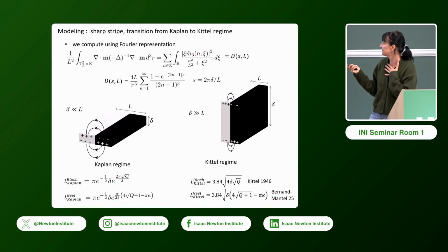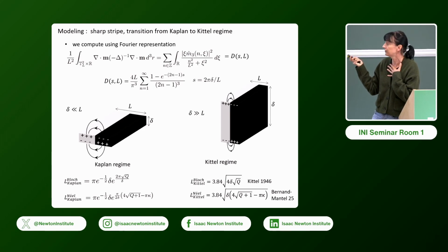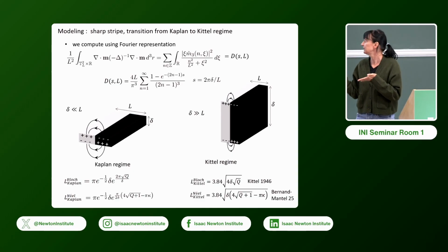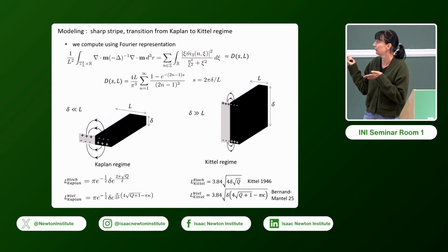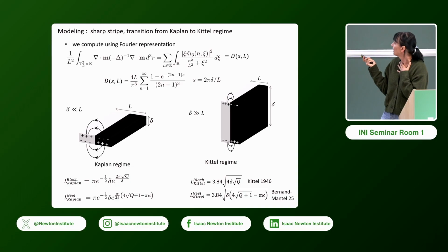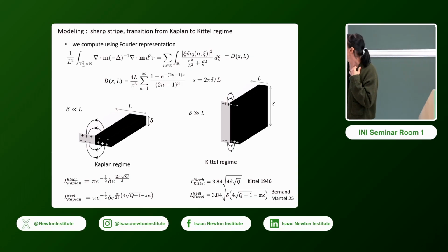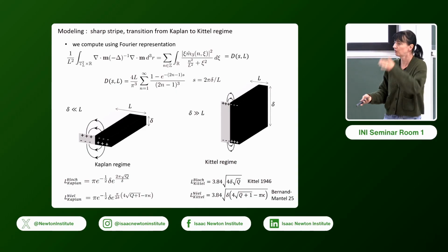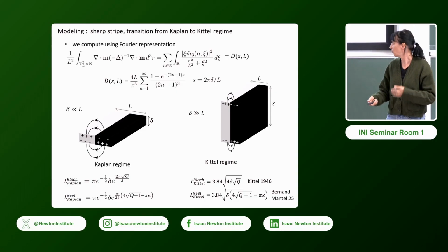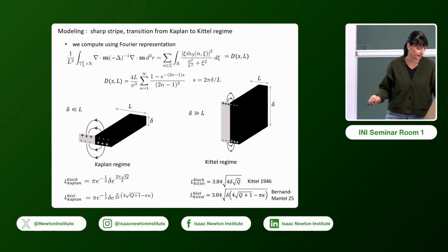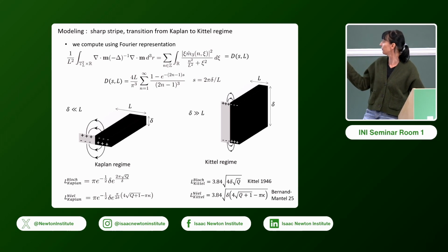And what is happening is that somehow the surface charges, which are contributing in a way that this alternation of surface charge is reducing the energy, are calculated separately and they are non-interacting. While here, it's not so interesting anymore because they are starting to compensate each other also from the top and the bottom. So these are two different regimes now that we see.